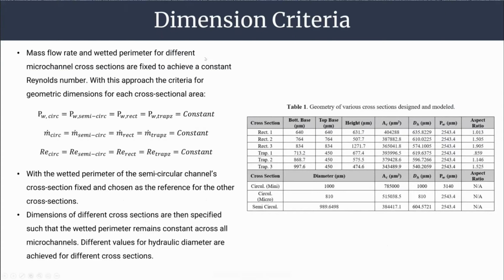As you can see, when we maintained a constant wetted perimeter across the shapes, we can attempt to maintain a constant Reynolds number across the different geometric shapes that we were working with. As I stated before, what was determining this was the semicircular dimensions. Essentially, they were the largest diameter, trying to fall below our 1,000 micron upper range and still have the rest of the shapes fall within the 400 to 1,000 microns. But we managed to develop 8 different shapes with the same constant wetted perimeter. And we developed several aspect ratios for the rectangular shapes and the trapezoidal shapes at regular, consistent intervals.